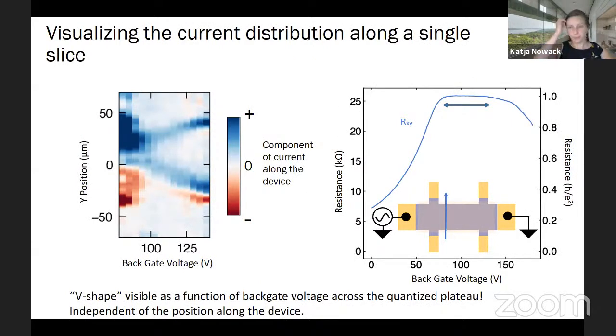We can take this one step further. Now instead of taking a full image, we only scan a single line across the sample, and then we continuously vary the backgate voltage. So what you see is a cut through the y direction of the sample, and on the horizontal axis is not a coordinate, but the backgate voltage. Essentially we tune the backgate voltage through this quantized plateau. And what is plotted is not the flux data, but we've already done a reconstruction. What is plotted is the component of the current density that flows along the device.